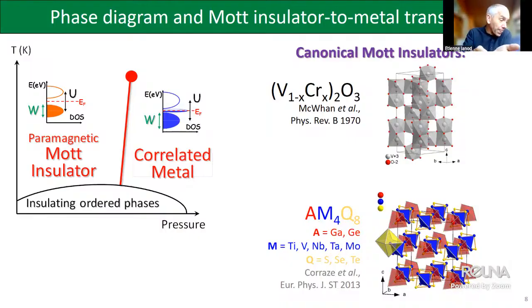Of course, I cannot give you more detailed experiment because we did not work on a specific perovskite, and so I cannot prove what I say. But my feeling is that the connection between the electronic degrees of freedom, insulator, metal, and the structure is through the unit cell volume, not degrees of freedom like tilting of the octahedra, which are inside of the unit cell. But okay, it has to be proven in a way because we never investigated perovskite directly, but indeed there are a couple of perovskites that are not insulators. You're right, and we might try to study them.